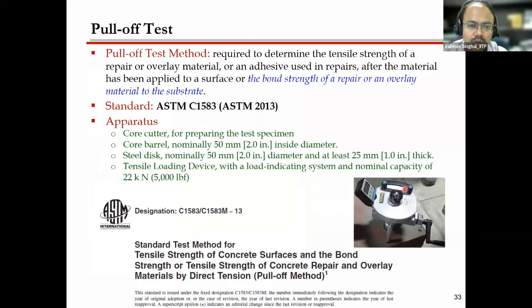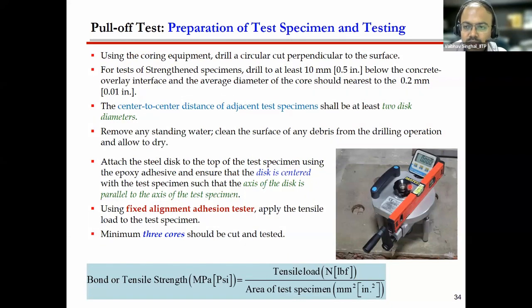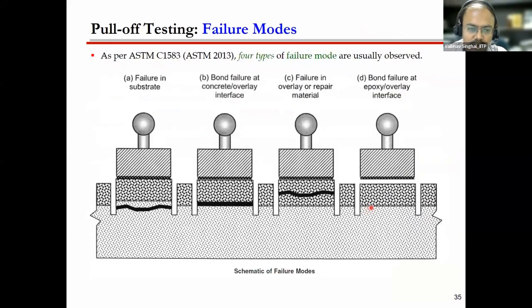Now, suppose you are unable to perform the bond test using the previous setup, another popularly used method is the pull-off test. For this pull-off test, you need some specific equipment. Generally the pull-off testers are available in various labs. So if you have this pull-off tester, you can use this pull-off test to find out how much is the bond strength between the matrix and the substrate, or between your reinforced cementitious matrix and the substrate. So this is a typical equipment you can see here. What is done is that we cut a core inside the reinforced cementitious matrix and till some depth of the substrate, and then a disc is attached to this core, and then this disc is pulled in the upward direction.